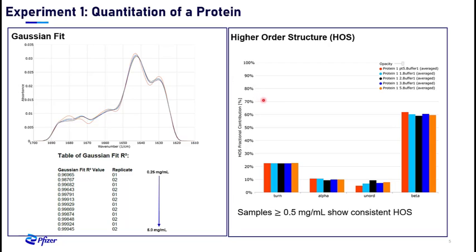This is more apparent on the right in the higher order structure bar graph, which shows the various secondary structure contributions to the analyzed protein. You'll clearly observe that this protein is primarily beta sheet. Higher order structure is very consistent for samples at half mg per ml or higher.